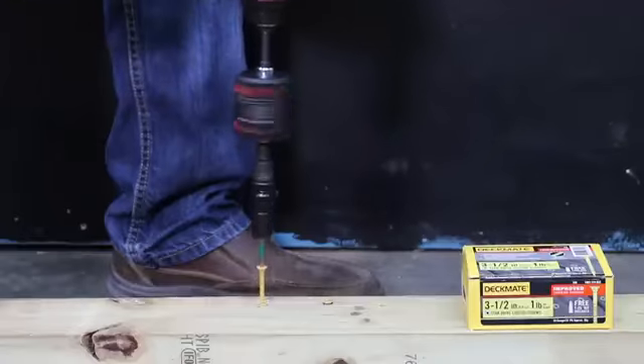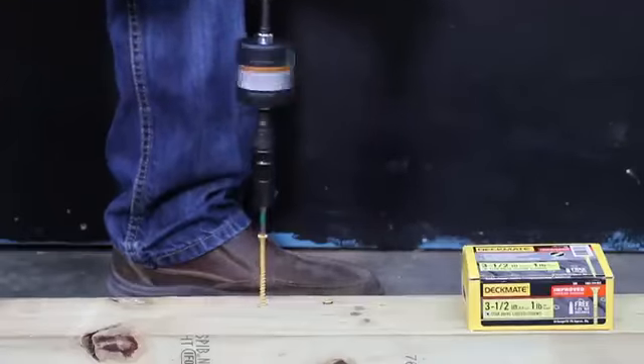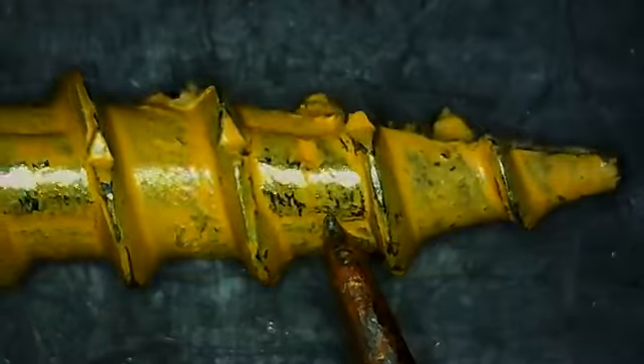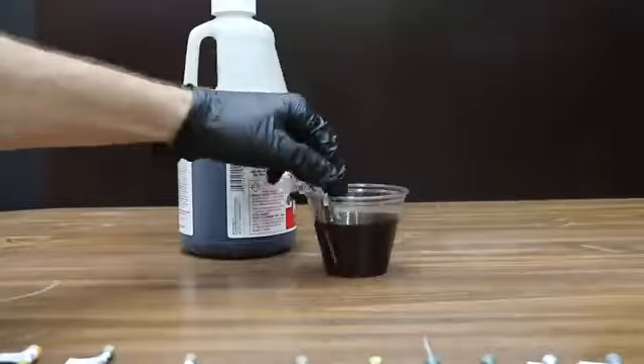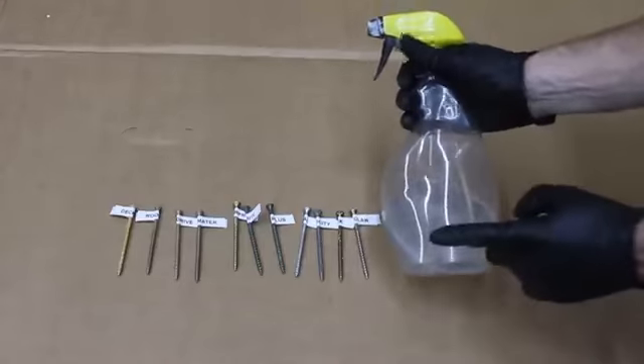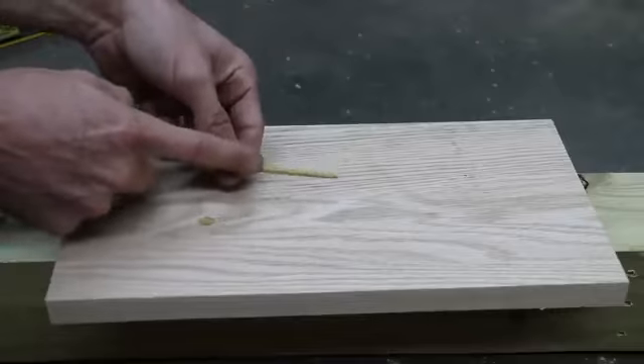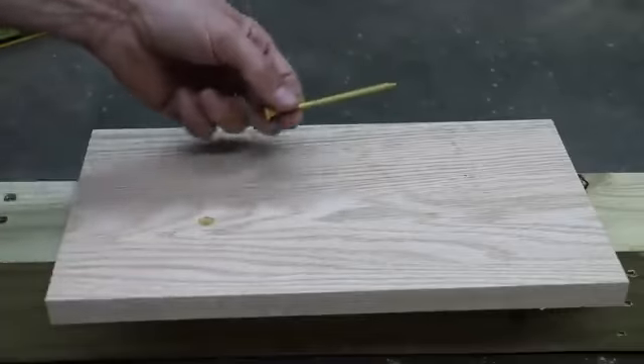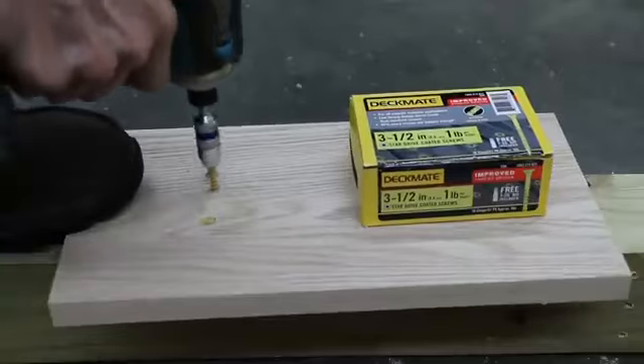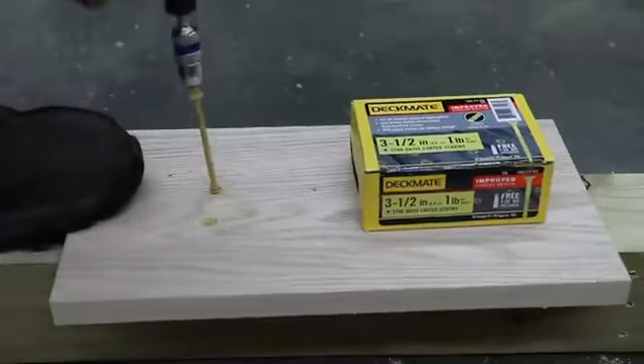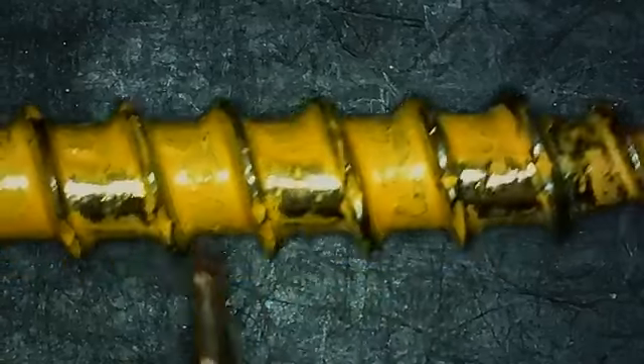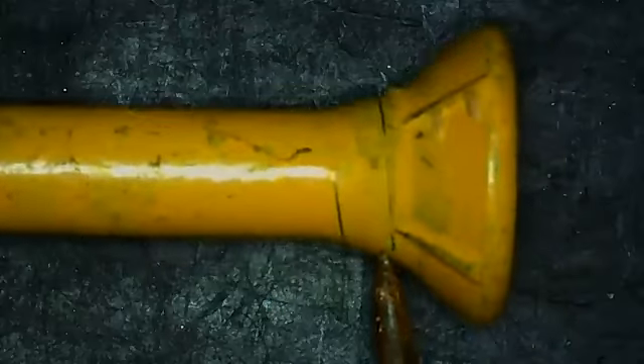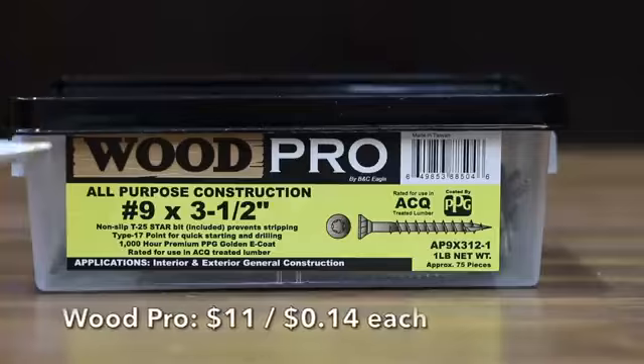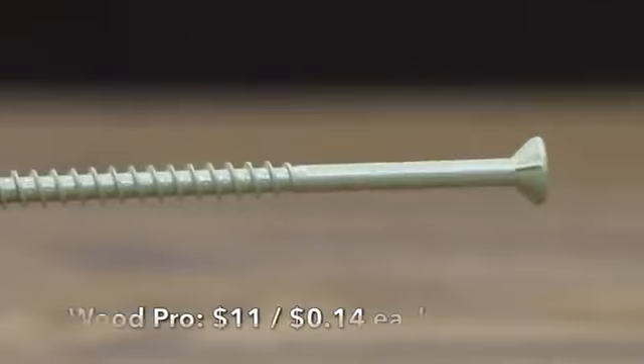I went ahead and removed all 3 screws, so let's take a closer look at them to see how the coating held up. And the coating experienced quite a bit of damage. It appears that there's now exposed metal on the threads and shaft of the screw. We'll expose the screws to a rusting agent later in the video to see if any rust forms on the exposed metal. Pressure-treated 4x4s are pretty soft, so let's use a new screw and see how the coating holds up after being driven through a 1-inch piece of oak and into a 4x4. And there's quite a bit of damage to the coating on the Deckmate with bare metal exposure on the threads and the shaft.